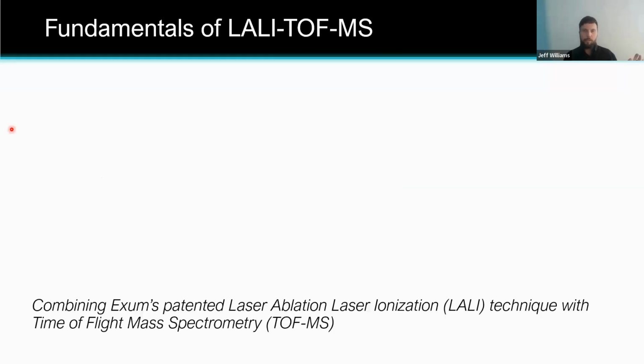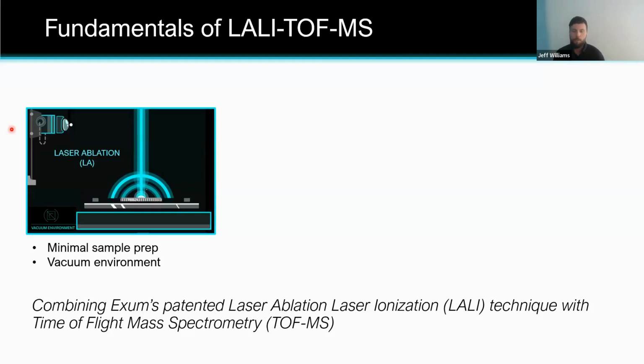So this is a laser-based technology. Some of you may be familiar with other laser-based technologies, and we do things a little bit differently here. We still do what's called laser ablation. So this is LALI, TOF-MS. I'm going to break down that acronym. So laser ablation happens. This is ultrafast ablation, so a picosecond laser. We don't have to go into the details of that. Happy to answer questions about it later. But really, we want to optimize for a neutral particle cloud being liberated from the sample surface that's stoichiometrically representative of the solid that we ablated from. And we don't want plasma and we don't want particles or molecules. We want to optimize for neutral atoms. So we have a special laser system that we tune just for this to happen.